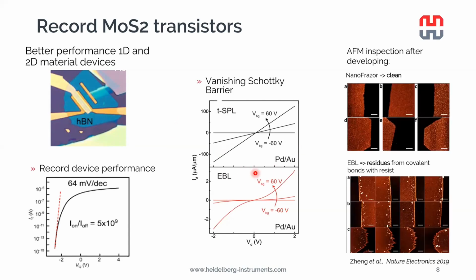One possible explanation why the devices perform so nicely could be that when we carry out AFM inspection of the MoS2 just after developing, so just before the metal deposition, the NanoFrazor samples are pristinely clean, so we don't see any modification of the material. While for the electron beam lithography patterned sample, we see residues from the electron beam resist. It has, as we say, burned on the sample. We also see roughening of edges, which is quite clear damage, which we attribute to the electron beam lithography process.